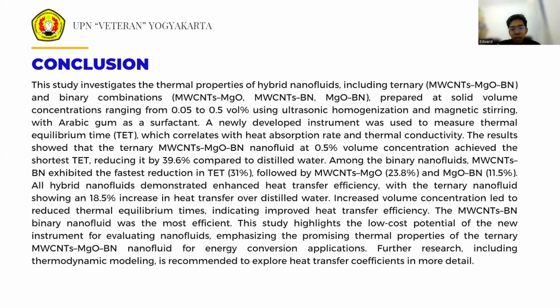Third, performance of the binary and ternary nanofluids. The study compared the performance of various binary and ternary nanofluids with different nanoparticle combinations, namely MWCNTs and MgO and boron, MWCNTs and magnesium oxide, MWCNTs and BN, and MgO and BN. Among the binary nanofluids, the MWCNTs and boron mixture proved to be the most efficient in terms of heat transfer, achieving a TET reduction of 31% compared to distilled water. This was followed by MWCNTs, MgO, and MgO-BN, which had reductions of 23.8% and 11.5% respectively.